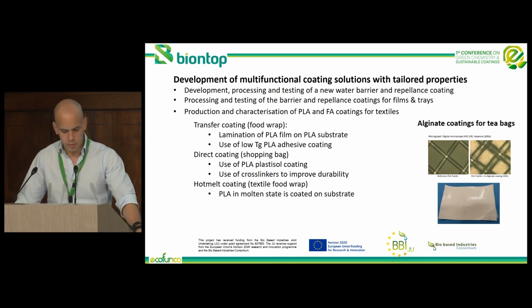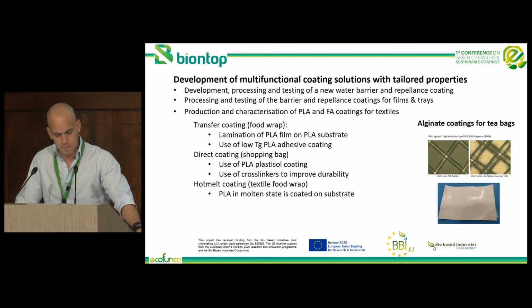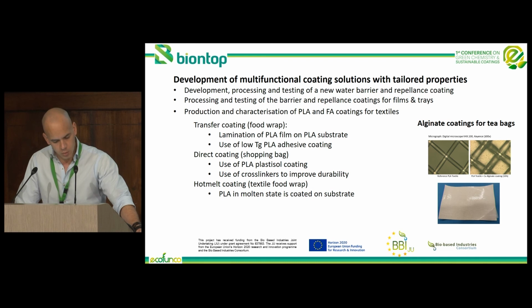And to finish, we are producing and characterizing PLA and fatty acid coatings for textiles. Here in the slides, you can see alginate coatings for textiles, for tea bags. Currently, we are following the different experimental procedures that you can see in the slide. We are currently updating and improving the glass transition temperature by screening of dispersing agents, and we are also improving the blocking coatings required and carrying out stain resistance and repellency tests.